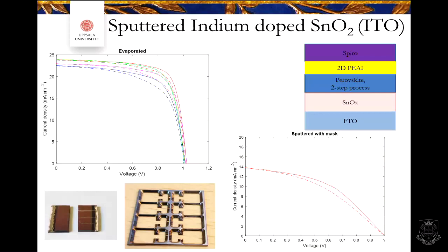Here we see an example of classical evaporated gold on top. And here we have an efficiency of approximately 20%, while for this sputtered version, you can understand from the curve and its meaning that it is not that good with sputtered ITO. But of course, the process can be optimized, and they can get better values. But this was one of the first tests to sputter ITO.